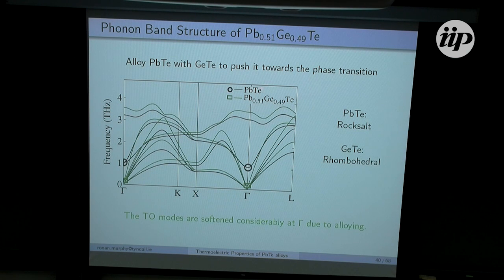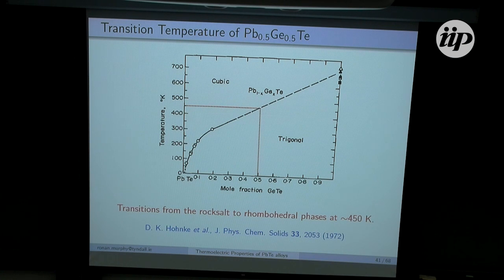So now if we consider this lead 51 germanium 49 alloy and take a look again at our phase diagram, you see it going up here, the phase transition for this particular alloy in reality occurs at about a temperature of 450 Kelvin. So this is just to point out the fact that we would expect our model to be most representative of the real world in and around this temperature. So when I go on to show you the thermal conductivity results for these lead germanium telluride alloys, I will be quoting them at 450 Kelvin.